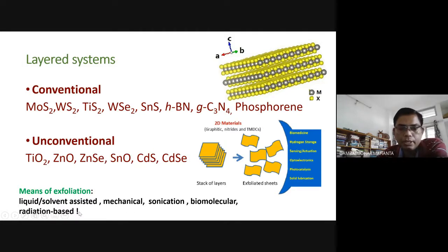Now, radiation based exfoliation is also a technique through which one can peel one layer from the other and make sheets. If radiation is falling this way, then because of a gradient in stress, this is going to come out of the rest of the stack. So if you have a stack of layers, a layered material, it could be graphite, it could be nitrides or TMDCs. We need to have sheets, and it is still very challenging to obtain monolayer sheets in TMDCs, that is, single-layer sheets. What we end up with are a few-layer sheets.